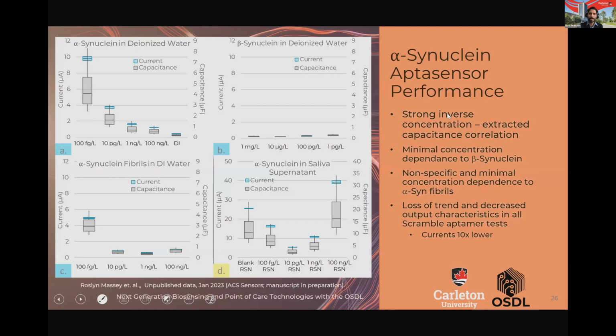And if we were to summarize this to show what we are seeing, on a linear plot you have a nice logarithmic dependence, which is great because that means that on a log plot or a semi-log plot, it's a linear response. Transistors are great at doing that over a broad range of concentration. So you see that our aptasensor can detect alpha-synuclein in synthetic samples. You also see that we can detect alpha-synuclein in saliva supernatant samples.